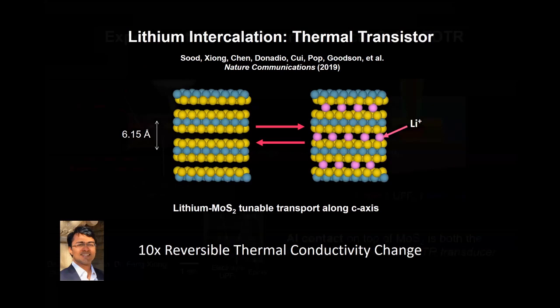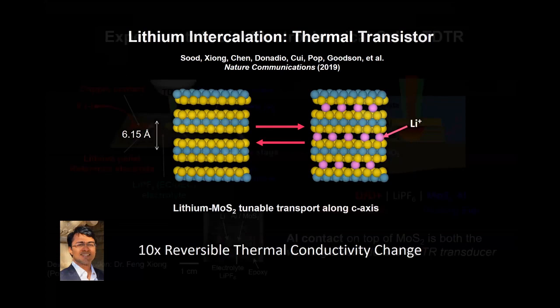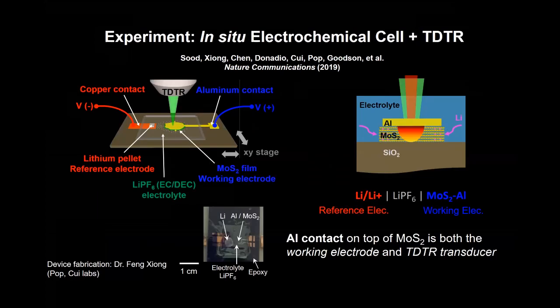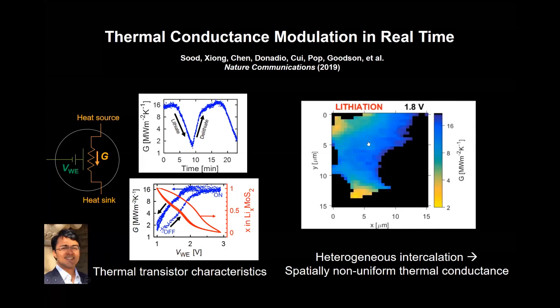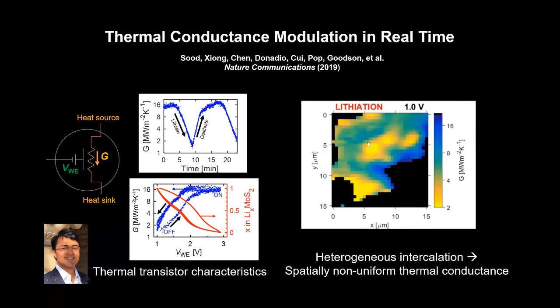And so he was able to put together a measurement where he was able to watch the thermal conductance change as the battery was storing charge, basically. And it was an order of magnitude change in the thermal conductivity. I have no illusion that this is going to work, but in case the image comes across, you can actually see the thermal conductance evolving as you change the voltage and drive the battery into storage and depletion mode. Very neat stuff. So with that, I'm wrapping up.